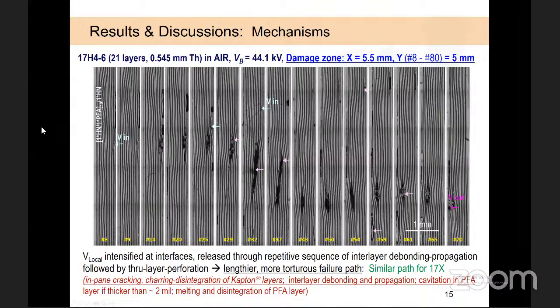As marked in the micrographs, you can easily find where the voltage broke in, propagated, and out. The complete damage and failure modes are listed in red, and their dimensions were also calculated. More importantly, it seemed that the local voltage was intensified at the interlayer interfaces and released through repetitive sequence of interface debonding and propagation, followed by through-layer perforation process, resulting in lengthier, more tortuous failure paths. Thus, one of the potential mechanisms was confirmed. A similar path was also observed from 17X sample.